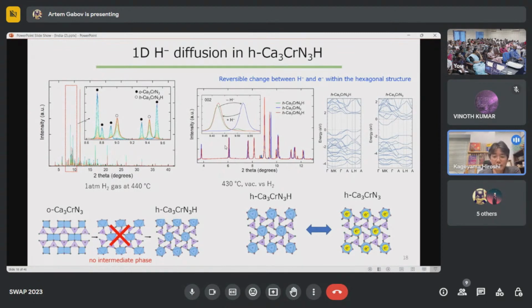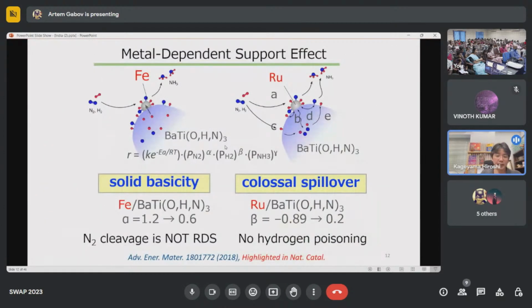So now we know that in this hexagonal material, with or without H, the hydride anion is migrating in the structure. Maybe this is very important for considering the high catalytic activity during the catalysis performance. Previously we demonstrated that in the barium titanium oxyhydride, hydrogen migration through the lattice plays an important role in the catalytic activity, because hydrogen can give a poisoning effect, so-called hydrogen poisoning. But hydrogen migration in this catalyst avoids such problems.